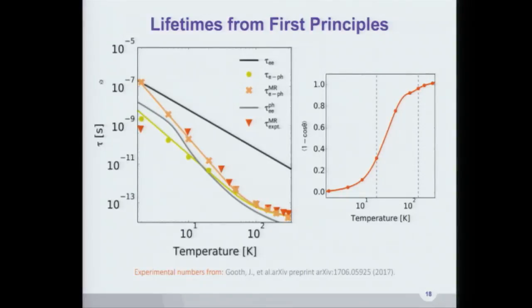So we started comparing these lifetimes, and we also started thinking about the small angle scattering, and we realized that actually it's not just the electron-electron scattering that dominates, but also the scattering that is this virtual phonon-mediated electron-electron interaction, so not the typical Coulomb interaction mediated, but the virtual phonon mediated, that starts to actually become very, very important in order to explain the emergence of a hydrodynamic regime in tungsten phosphide.